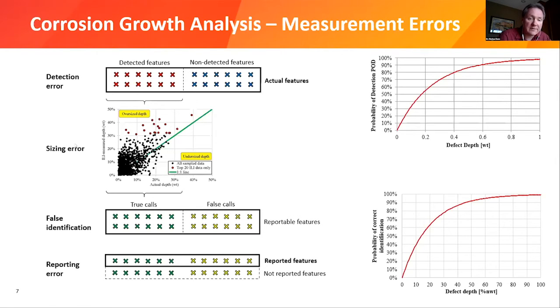Then the next type of error we have is a so-called sizing error. That is, the actual size in the pipeline, let's say the percentage of wall thickness, is different than what the tool is telling us. So here is a scatter plot where I have the actual size in the pipeline on the horizontal axis and the reported size on the vertical axis. If you would have a perfect tool, all those defects would lie on this one-on-one line, the green line here. As you see, that is clearly not the case. There's quite a spread and quite some sizing error contribution when it comes to corrosion growth. If you assess the corrosion growth based on the change of the measured size, you often see that close to 50% of your defects don't grow or they have a negative growth. And this negative growth is just due to the sizing effect because it is so dominant.